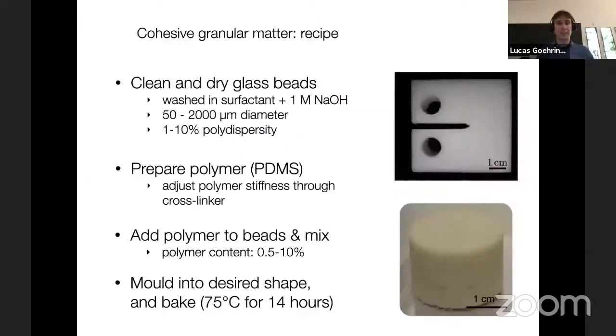A recipe of that is basically we take glass beads. They can be anything from the range that seems to work well, about 50 microns to millimetric beads. We can use polydisperse systems or not. They need to be clean in order to have good bonding to the PDMS. But we take a pile of beads, we add a few percent of a liquid polymer. We can adjust the stiffness of the whole system by changing the stiffness of the polymer, by adjusting the amount of cross-linking agent that we add to that. More cross-linking agent means that the polymer is harder, less means it's softer.